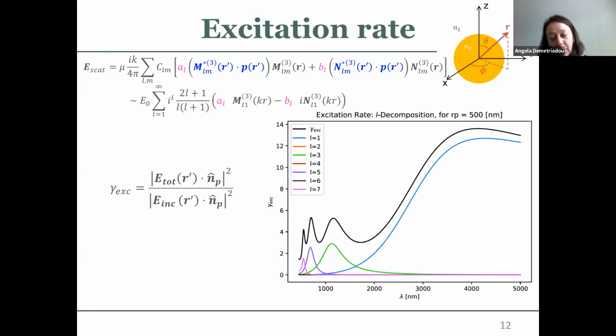And if I plot the same thing for the excitation rate now, I see the full result, with all my modes, is the black line here. Now for the same nanoparticle, 500 nanometers in radius. And if I decompose my modes, this is the first order mode, this is the third, this is the fifth, and this is the seventh. And I immediately see that I'm missing all the even modes from this system.